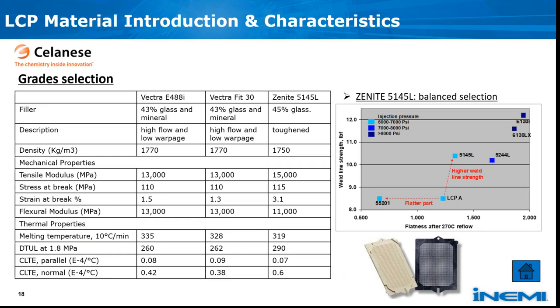For this study, 3 LCP grades were selected, considering the flowability, warpage resistance, especially that after SMT, and also taking into account the weld line strength, which is important during stitching. They are, in the left picture, Vectra E488i, Vectra fit 30, and then Zenite 5145L. The prior two grades are glass and mineral reinforced, while the last one is only glass reinforced. Please refer to the figure for more detailed properties.